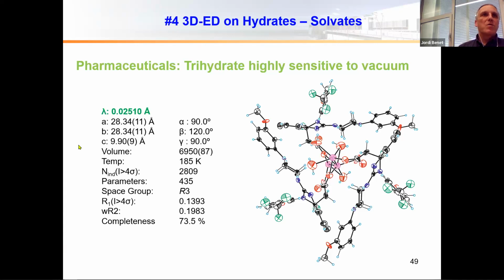And the reason was because we had again, let's say, high symmetry. It was a hexagonal cell or a trigonal cell, and we could get a completeness of 73%, an error value of 13, or let's say 14%, and a good ratio of reflections to parameters. And of course, we could localize the water molecules so that we could characterize this hydrate without problems using cryopreparation.